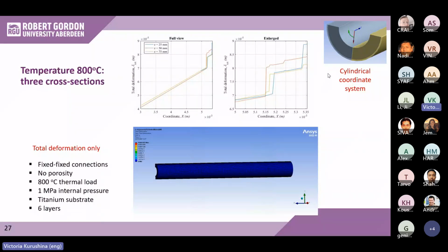Okay, so the total deformation results in this slide are now presented for 3 cross sections in the middle. They are evenly spaced: if we have a tube which is 100 millimeters long, these samples are taken from the 25, 50, and 75 millimeter marks, counted from one of the fixed boundaries. They show a very similar increase in the total deformation value with the radial coordinate, where 3 is the radius of the internal gas channel. So this internal radius is 3 millimeters here. This is the total deformation which comes through the wall.